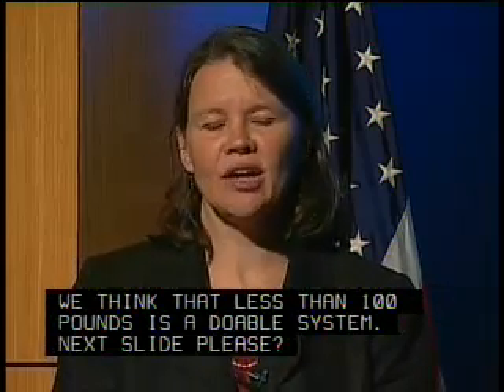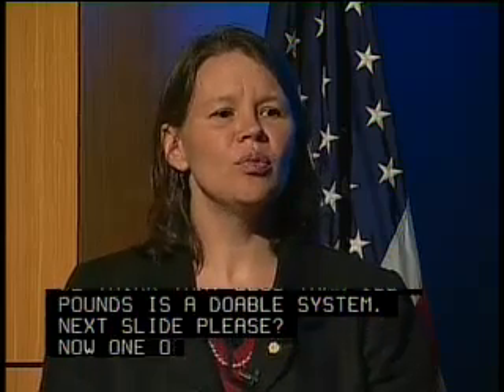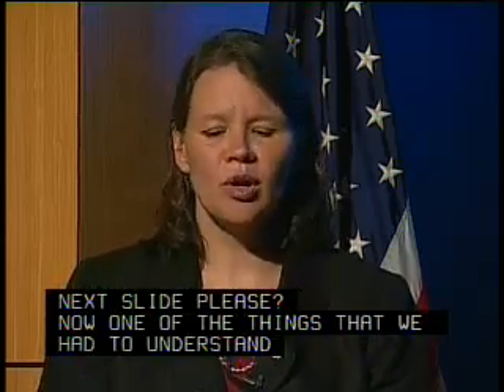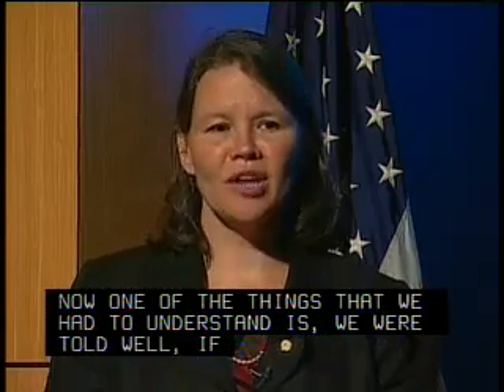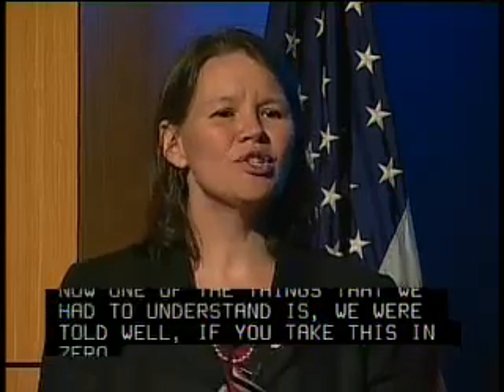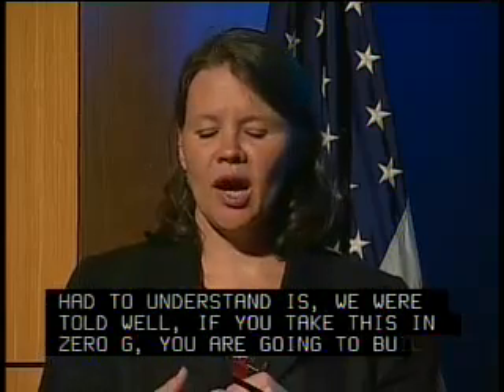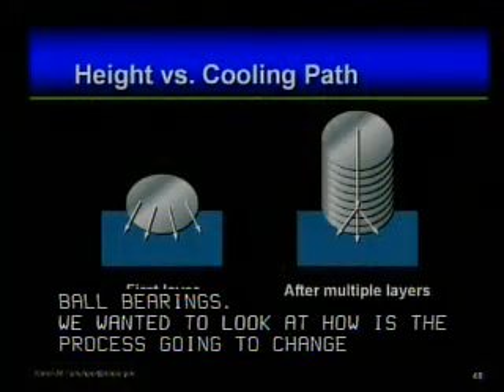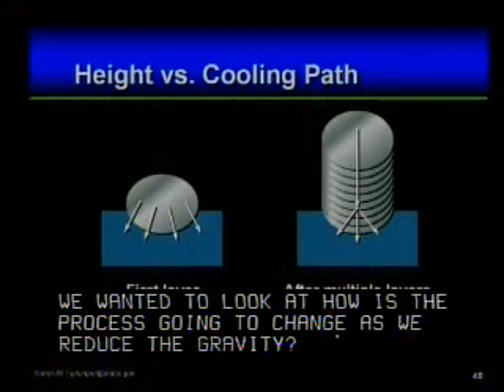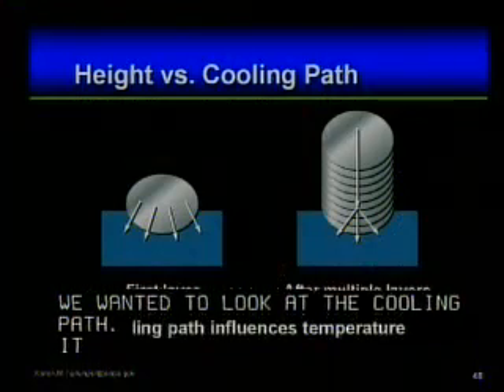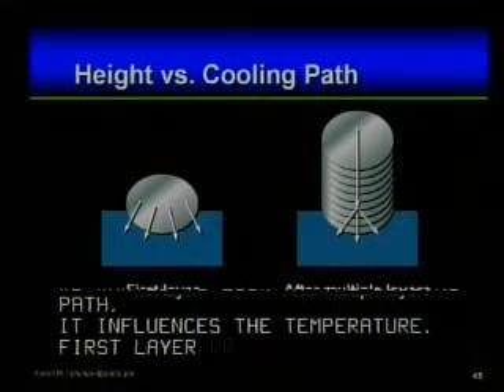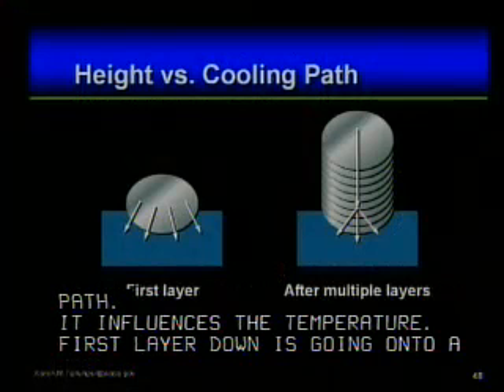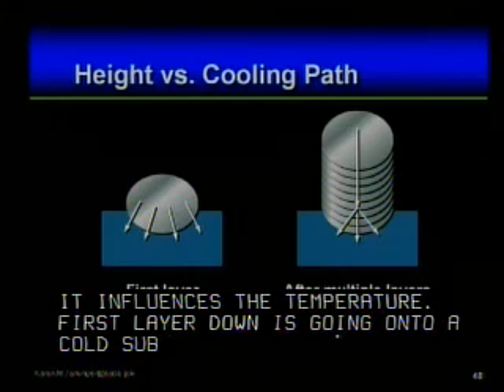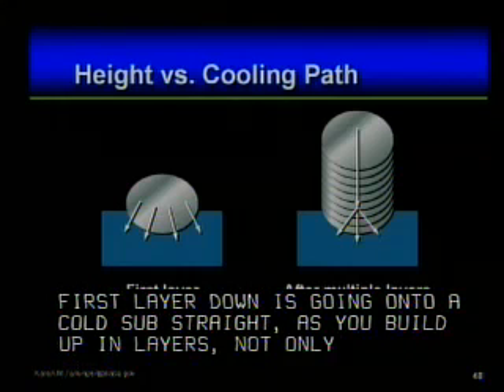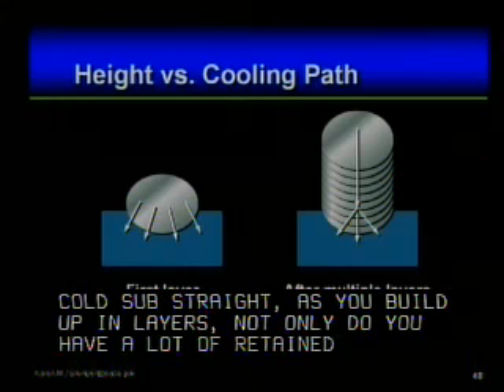Now, one of the things that we had to understand, and we were told, well, if you take this in 0G, you're just going to build ball bearings. And so we wanted to look closely at how the process is going to change as we reduce the gravity. First thing we wanted to look at is the cooling path, because we know that the cooling path influences the temperature. First layer, just like in the residual stresses, first layer down is going onto a cold substrate, and so there's plenty of thermal mass to cool that bead down. As you build up in layers, not only do you have a lot of retained heat because you're building onto something hot, but you've also reduced the cooling path down through the part that you've built.